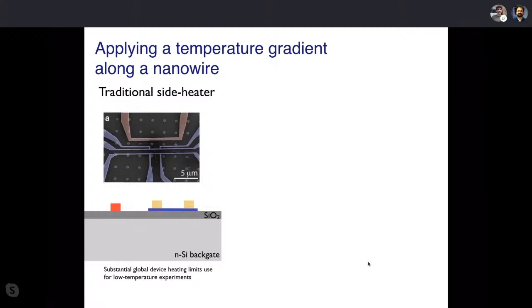The other thing we needed was the ability to heat our system, to apply a heat gradient in particular, while maintaining a low temperature. So we want to use quantum dot physics, which basically means you want to hang around 1 Kelvin, maybe up to 4 Kelvin, 10 at the most, otherwise you lose your quantum dot physics.